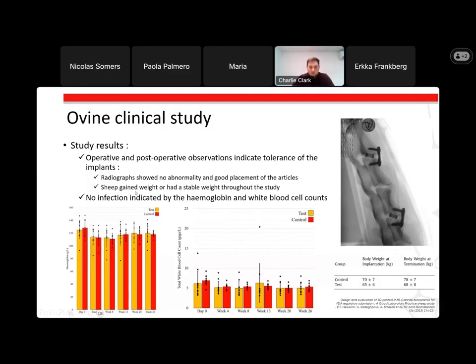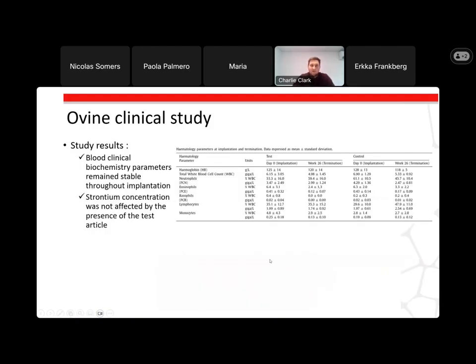And we can see there was no infection by controlling the levels of hemoglobin and also the white blood cell counts, which obviously would increase if there was any infection that they were trying to fight off. We could see that there were good blood clinical biochemistry parameters. They remained stable throughout the implantation. The strontium concentration was not affected by the presence of the test article. It's important. The strontium inside the test article is what's going to help the bones fuse together without having to use the autograft. But ensuring that the strontium then doesn't become wayward inside the sheep's body is also very important.